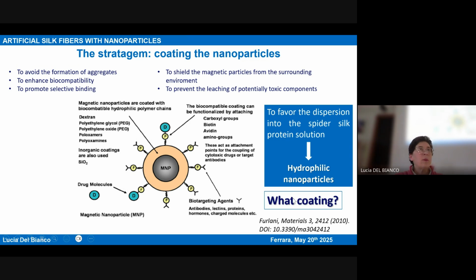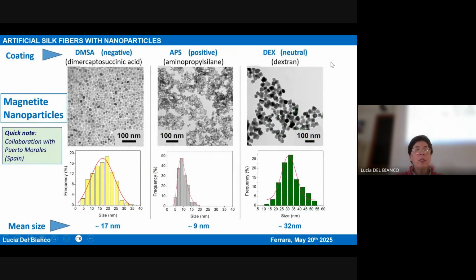But what coating? It's not so easy. There was not an easy answer to this question because nobody did that before. And therefore, what coating? No answer. And therefore, we tested 3 different types of nanoparticles with different coatings. DMSA coating, this was an acid. This was APS coated, a compound of silicon. And the dextran is also a biopolymer, actually. And these different types of coating also resulted in a different surface charge around the nanoparticles, so negative, positive, and neutral. And the particles also differ in their mean size.